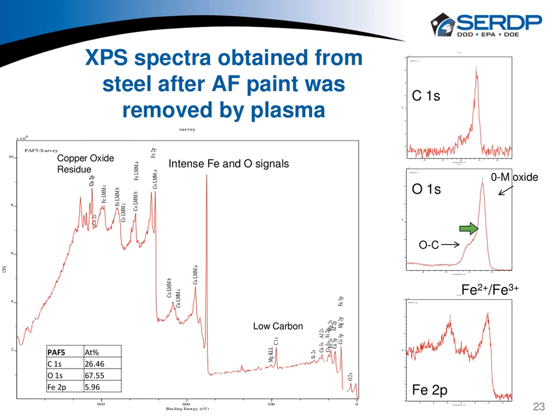And then if we look at the iron surface, in this case, there's no observable peak due to iron oxide, to the metallic iron. It all appears to be oxidized. So this is giving us the first indication of the thickness that oxide may be. It has to be at least 100 angstroms or so, because we're not seeing metallic iron on this sample. I guess that's all I want to talk about on that.